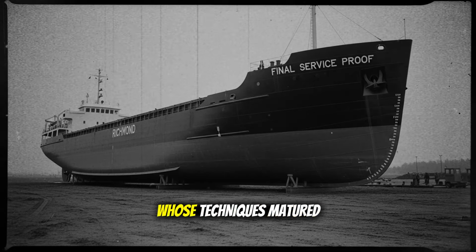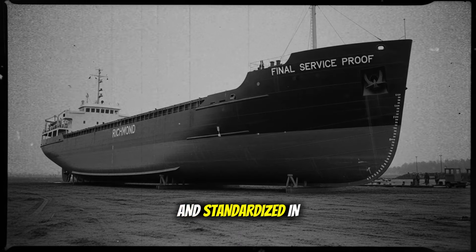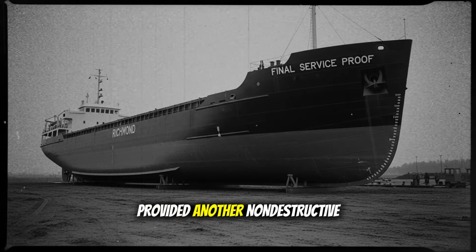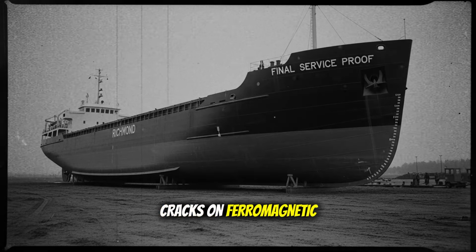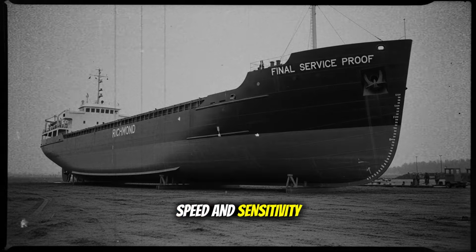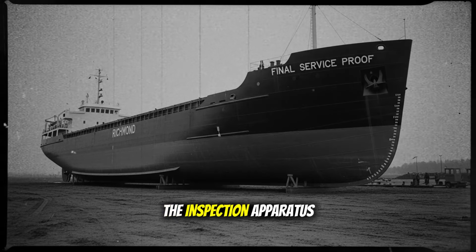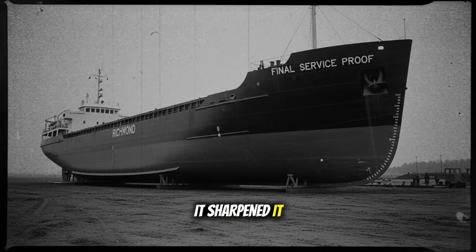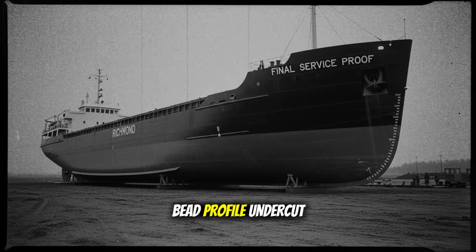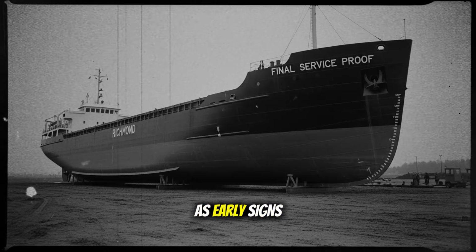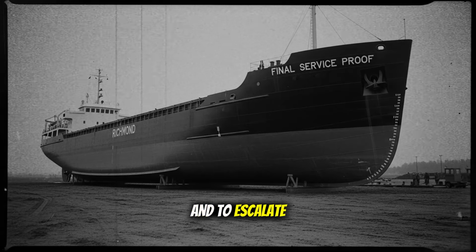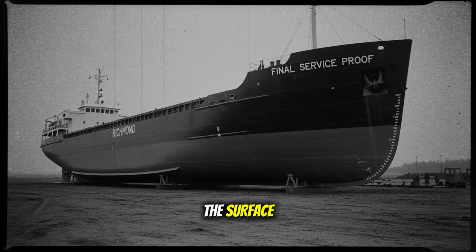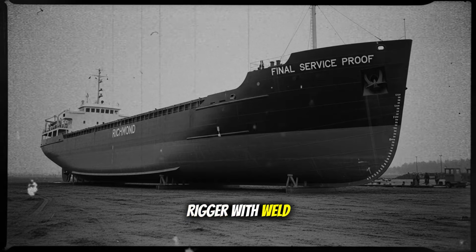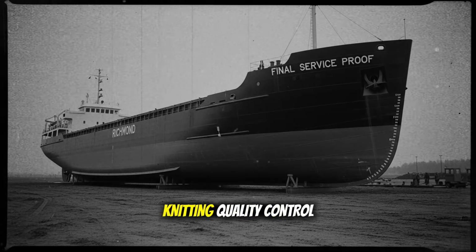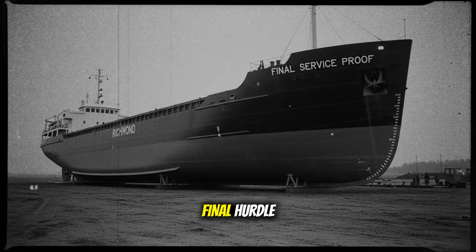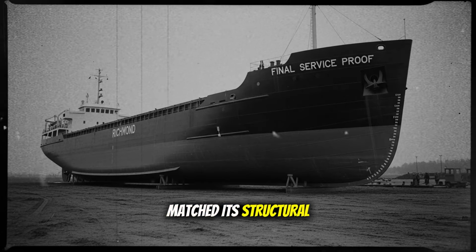Magnetic particle inspection, whose techniques matured commercially in the 1920s and standardized in industry by the 1930s, provided another non-destructive eye for surface-breaking cracks on ferromagnetic weldments, complementing radiography with speed and sensitivity where it fit the work. The inspection apparatus didn't eliminate visual craft, it sharpened it, training crews to see heat tint, bead profile, undercut, arc strikes, and toe blending as early signs of how a joint would live under load, and to escalate what couldn't be trusted to methods that could see beneath the surface. Documentation followed the rigor, with weld maps, repair logs, and inspection records knitting quality control into production rather than treating it as a final hurdle, so that a ship's documentary trail matched its structural truth.